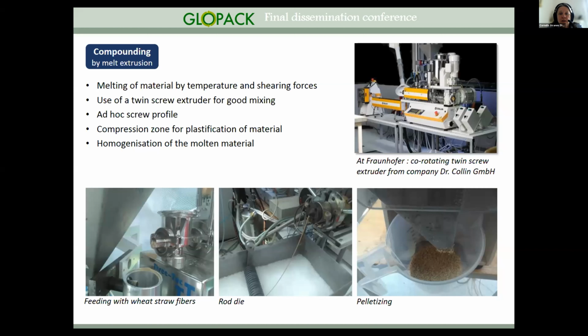On the picture on the left side you see first the dosing unit for the polymer, and then the feeding unit to add these further ingredients. Then you see in the middle the strand extrusion of the mixed polymer or the blended polymer. After cooling, normally in a water bath, a pelletizing step follows to make granules of the material.